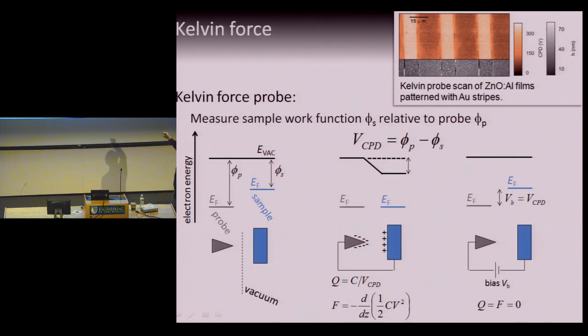And the way that this measurement works, actually, a small measured value means a high sample work function and vice versa. So here I've scanned over a sample with lithographically defined gold fingers. And by measuring the difference between this level and this level, and this is now in voltage space, so this color map is a function of voltage, I can measure the difference in work function between my material and gold. And in practice, you would just make a histogram of values and fit two peaks and look at the separation between those two peaks, and thereby get the difference in work function. So that's how we measure work function, and that was actually kind of neat.